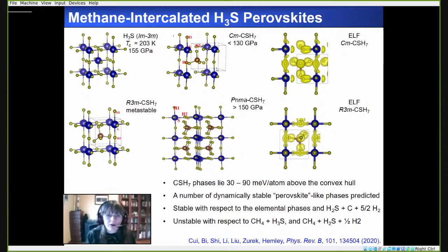So we predicted a number of metastable phases, and all of them were built from this type of building block, where you take one of these interpenetrating H3S lattices and replace it with a methane molecule. And then you can imagine different sized supercells where you have different methane molecules in different neighboring cells, rotated slightly differently. So we predicted a number of phases that were most stable at different pressures, with this PNMA phase most stable at high pressures.